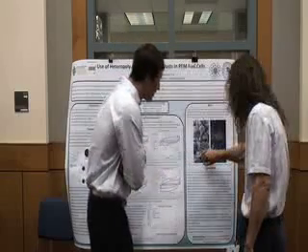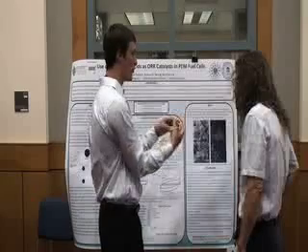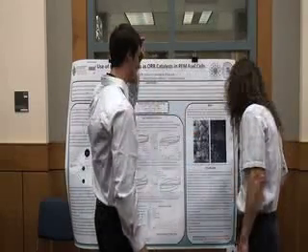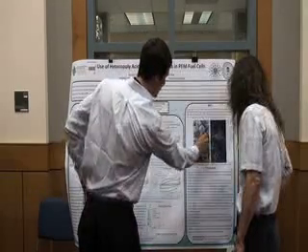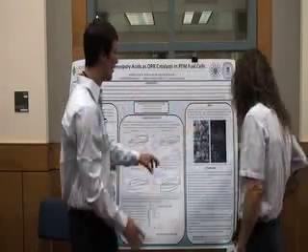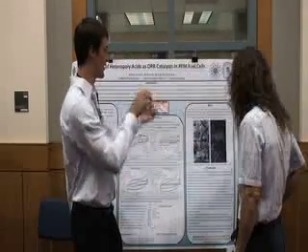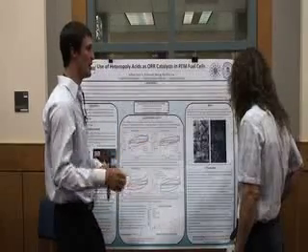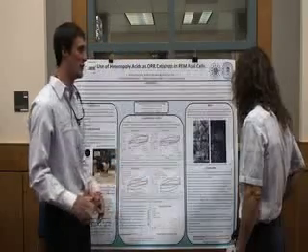So wait, one of those little things is what? That's a crystalline type structure of multiple PW11s. Whereas the little tiny dots are single silicon tungsten 11 molecules. So here's the control for that one. Here's the silicon tungsten molecule, and they're really spread out and dispersed. Whereas the PMo11 and PW11 have created this crystalline type structure. So that could be part of it: because you have to put the platinum on first, when you put these on there, it could be creating some sort of odd dispersion that doesn't allow the PMo11 to act like it does when it's by itself.